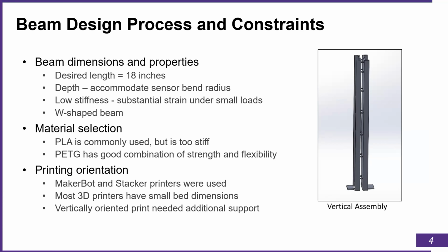So with the beam dimensions, we decided to go with 18 inches for a couple of reasons. We wanted, one, for students to be able to see this clearly, so we didn't want it to be too small. And then also with the Luna equipment, with the strain sensors, the smallest sensor they have is a 1 meter fiber. So we needed it to be big enough so we could get the entire fiber embedded into the beam. So with the depth, it was also dependent on the bend radius of the sensor. It has a specific bend radius, so we needed to make sure that it was large enough to accommodate that sensor.